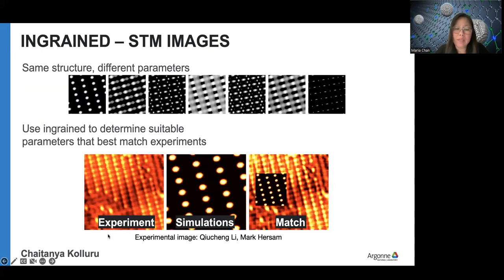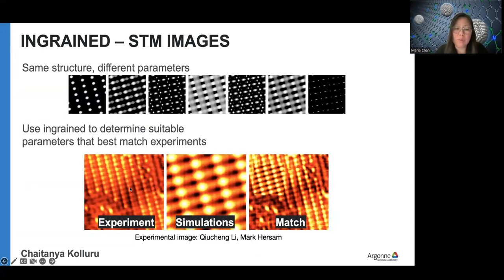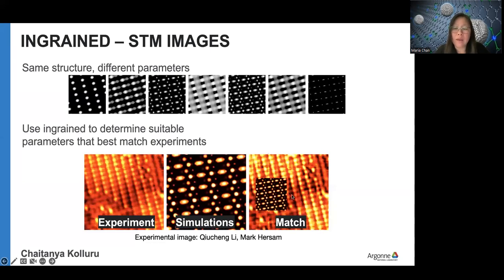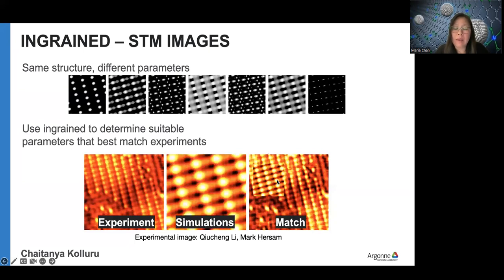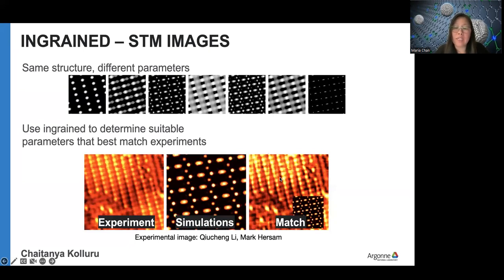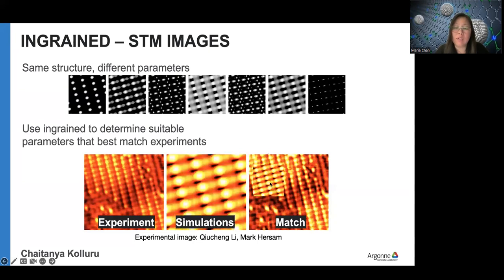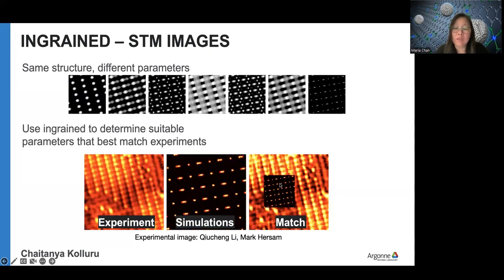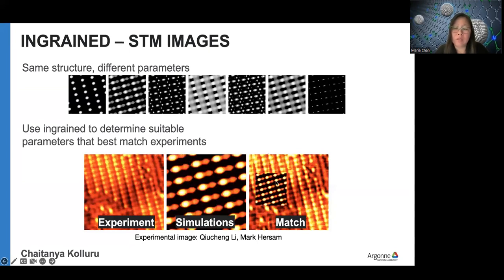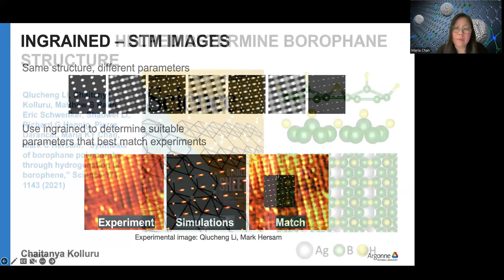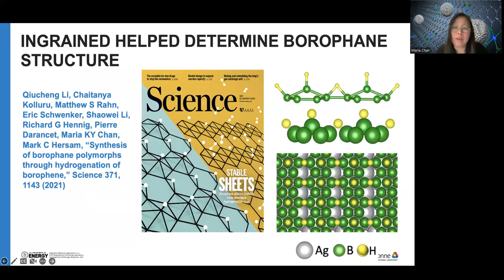And you can see here as an example a surface from Mark Hersam's group at Northwestern. Experimental images on the left, it doesn't have to be perfect. The simulation looks at a smaller patch of it, and then Ingrain carries out the simulation, as well as the optimization of the parameters, and which part of the experimental image fits that simulated image best. So as you can see, when the similarity progresses, at the end, it kind of looks like it almost melts into the experimental image.